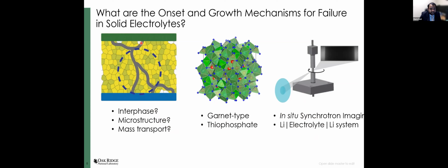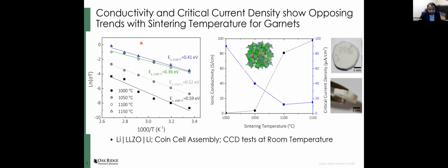And so we'll dive quickly into some results that we've gotten over the last few years. What I'm showing you here is the correlation between the sintering temperature of a garnet solid electrolyte. A garnet solid electrolyte is a kind of polycrystalline material that we can make that is a lithium ion conductor. And what we see, if you see this graph on the right, is that as you increase the sintering temperature, the ionic conductivity increases. That's the black curve here, while the critical current density decreases.